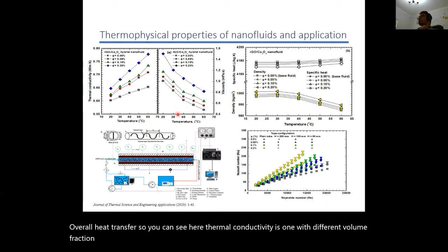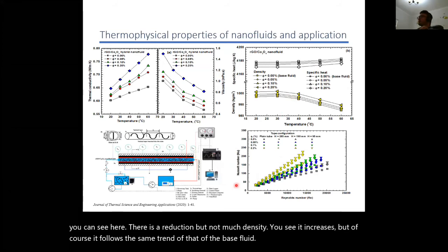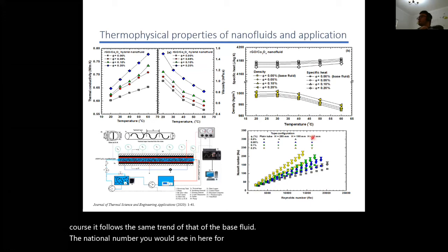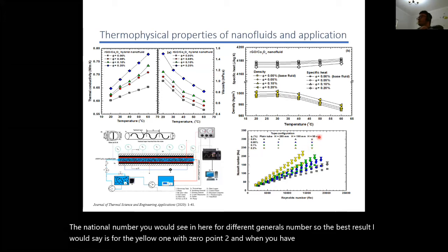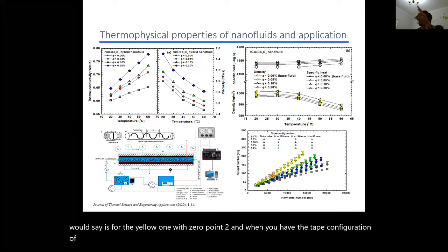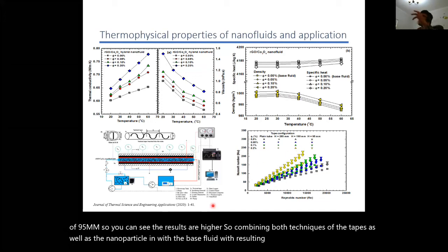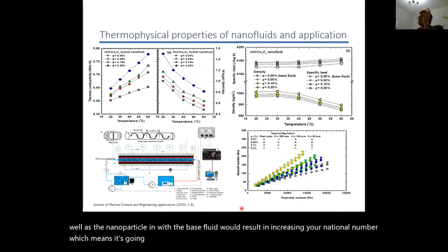volume fraction. Specific heat, you can see there is a reduction but not much. Density, you see it increases, but of course it follows the same trend as that of the base fluid. The Nusselt number you would see here for different Reynolds numbers. The best result, I would say, is for the yellow one with 0.2, and when you have the tape configuration of 95 mm, you can see the results are higher. So combining both techniques, the tapes as well as the nanoparticle in the base fluid, would result in increasing your Nusselt number, which means it's going to increase the overall heat transfer.